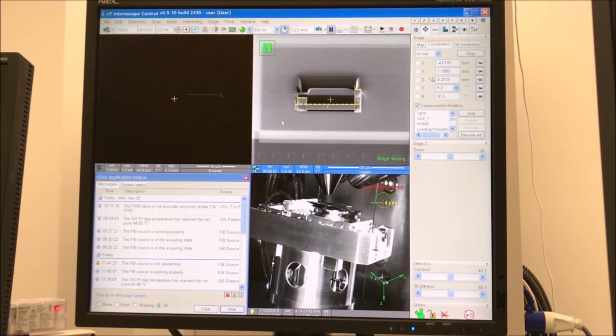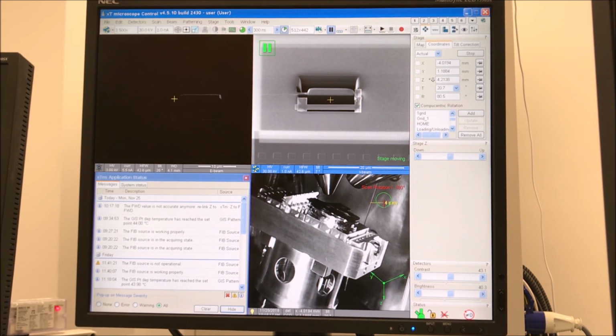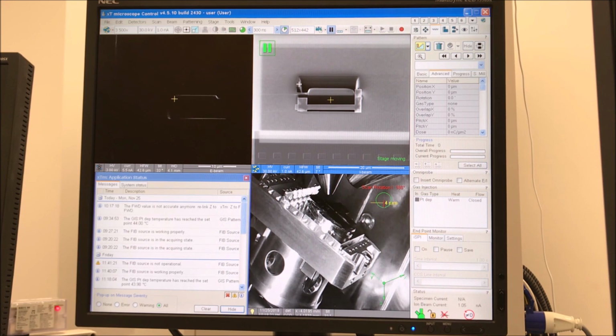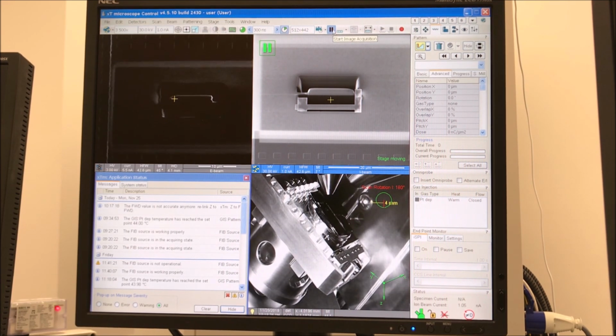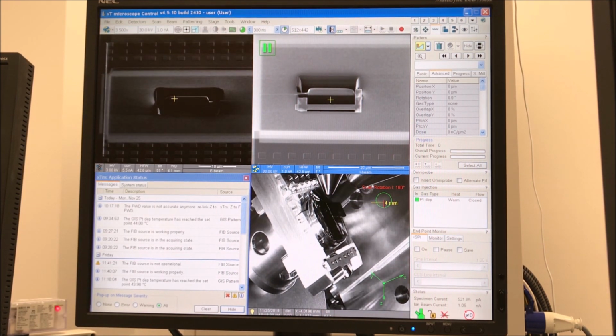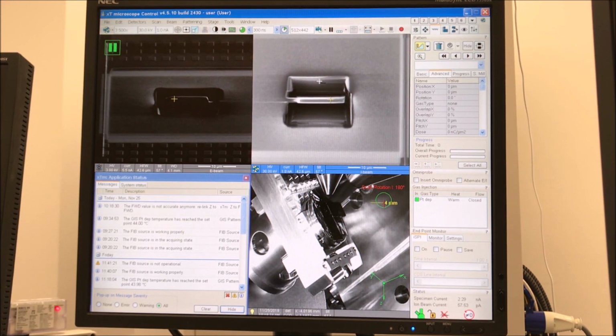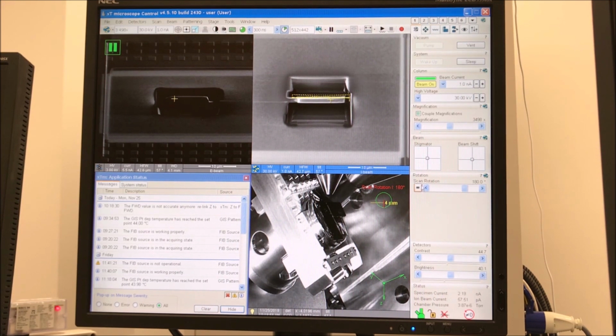Okay, so I stopped it, and now I'm tilting back to 57 degrees, and there's one more step we're going to perform before doing the lift out procedure. So once I get back to 57 degrees, I can shift the image back with the shift knobs, and now I'm using a cleaning cross section with a rotation of 180 because I'm performing this pattern on the top side of the lamella. So you can see there's actually a little bit of bowed out area, which typically happens after you do the undercut. And so this is just to clean that off.